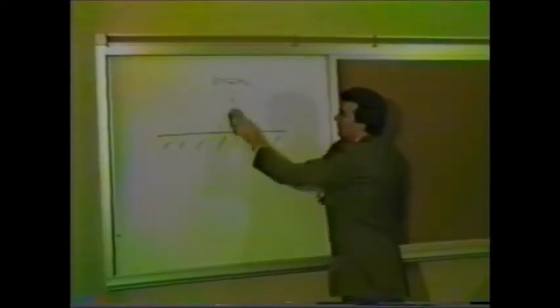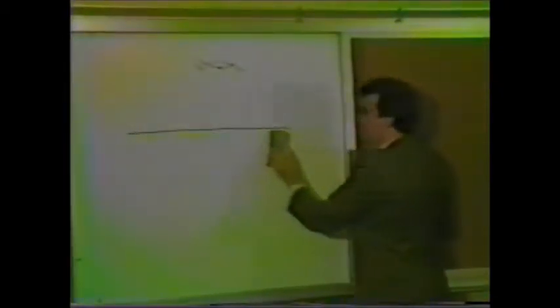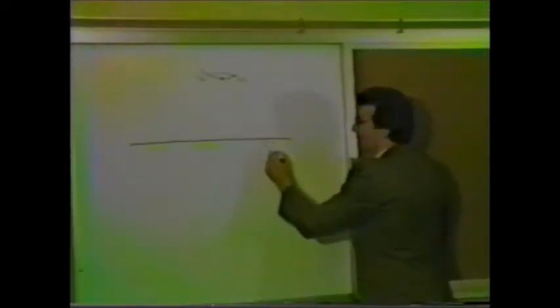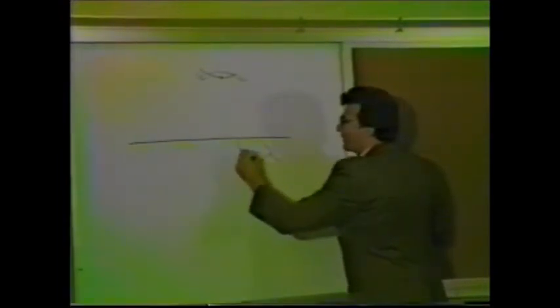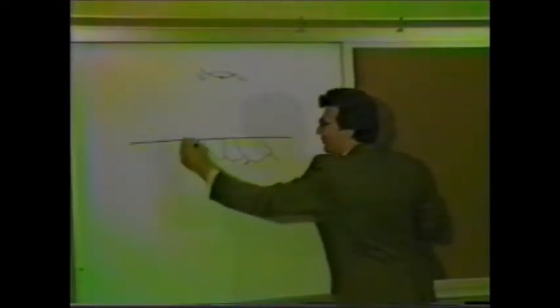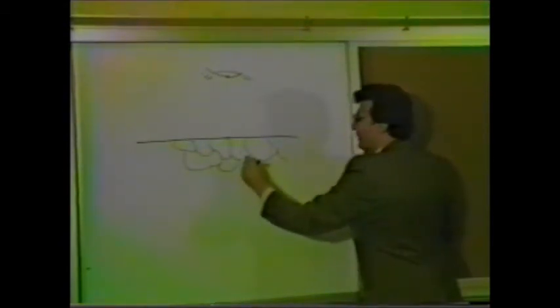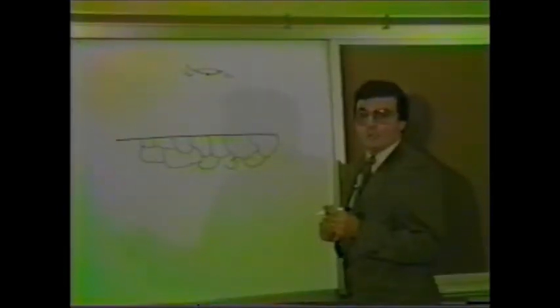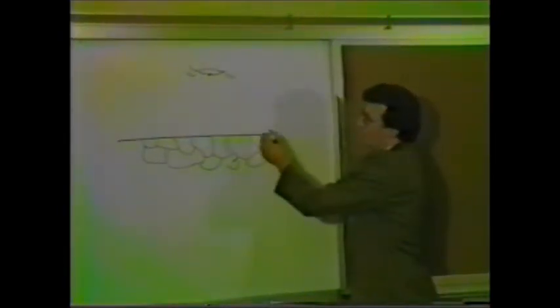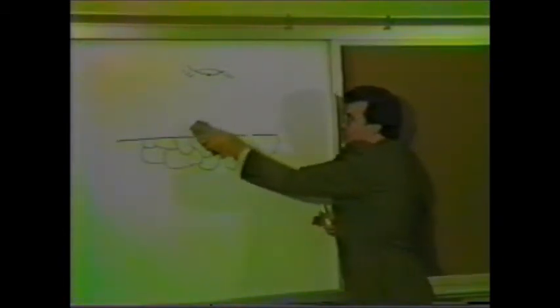And what we have to do on this piece of steel to see what the structure is underneath. In fact, I'd like to just draw a few of the grains of steel underneath that happen to intersect the steel that we're looking at here. Bear with me just for a second. Now, what we do is we etch the steel with a very light solution of hydrochloric acid in methyl alcohol called nital. And what we do is we'll dip the surface of the steel in the acid, and the effect that it has is that it eats away the steel.